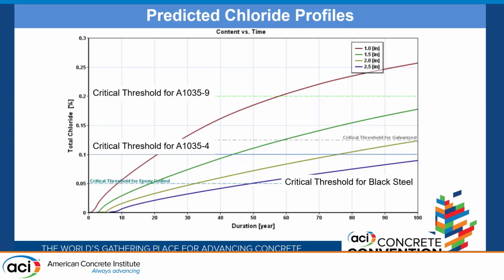The threshold line for stainless steel, and this is above the charts of stainless steel, would not be expected, at least for this concrete in this time period, to have chloride above the threshold value. The threshold value for the A1035 9% is that upper line up here, and other than 1 inch of cover, which nobody would use, nothing. It's going to be way beyond chloride initiation.